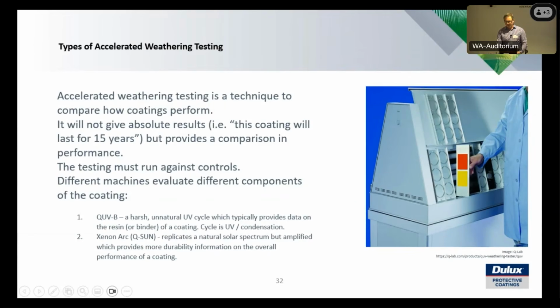So the QUV testing regime, there were 4,000 hours each. I'll get to that in a minute, but the QUVB was 4 hours of light, QUVB light, and then 4 hours of condensation at 50 degrees. The QSUN was a cycle of 3 hours light at 63 degrees and 1 hour dark water spray at 25 degrees. So constant testing there.